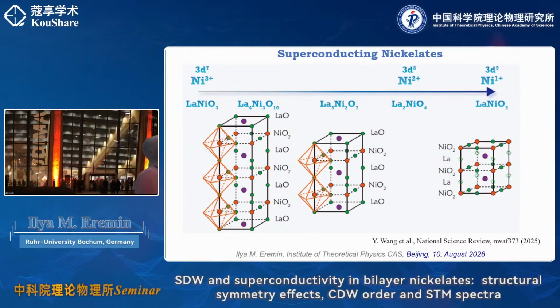This is also an active field of research. Meanwhile, under pressure, the system reaches 70 Kelvin. We still don't fully understand the system because it turns out that it's not exactly the same as a cuprate. So the physics is not a pure 3d x² minus y². There are obviously some other orbitals involved, and we don't fully understand this.